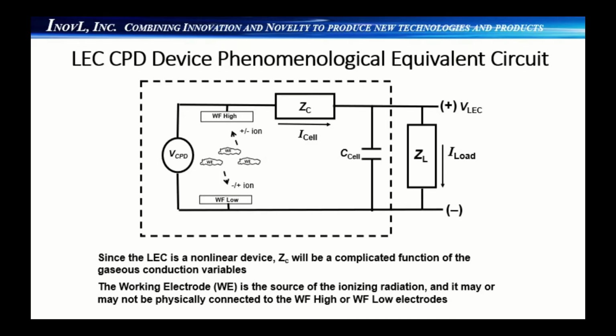This slide shows a possible phenomenological, physical, and electrical representation of the behavior of an experimental LEC contact potential difference device. For this representation, the working electrode, WE, is the ionization source, and as shown, it is not physically attached to either of the counter electrodes. The contact potential difference is due to the dissimilar work functions of the two counter electrodes, and is represented by the voltage source VCPD. The cell's capacitance is represented by C cell. The cell's internal impedance is represented by ZC, and the cell current I cell connects the voltage source to the external load impedance ZL. Thus, I load should be equal to I cell.